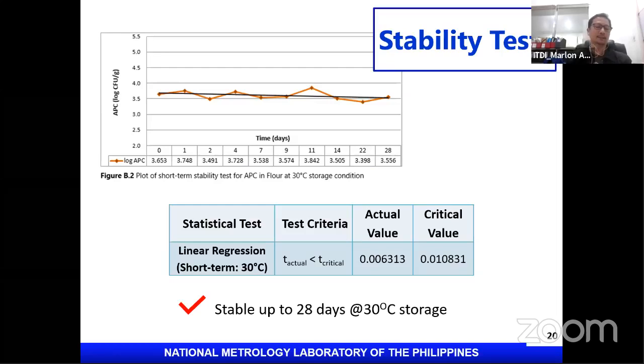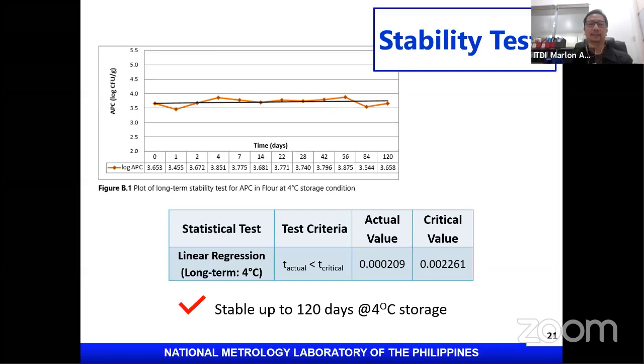The next thing we did was to conduct stability testing. This is the result of our stability test. Ang requirement dito is there should be no significant difference in the concentration of our analytes over a period of time. Based on linear regression analysis, the PT material was stable up to 28 days at 30 degrees centigrade storage. Aside from the 30 degrees centigrade storage, we also conducted stability testing of our PT material at 4 degrees storage. For this storage condition, we were able to achieve stability up to 120 days. We wanted to continue the testing. However, wala na kaming samples for testing. So hanggang 120 days lang yung aming na-achieve for this.